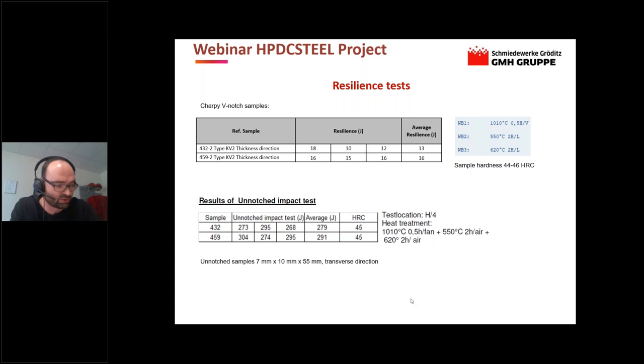Another option would be to quench especially Charpy V notch samples by oil, which according to our experience will even bring higher toughness results. But overall, these resilience results confirm the previously made simulations at industrial scale. We are very satisfied with these results. In any case, we understand that the material, by its resilience and its toughness, is able to prevent microcracks from growing.